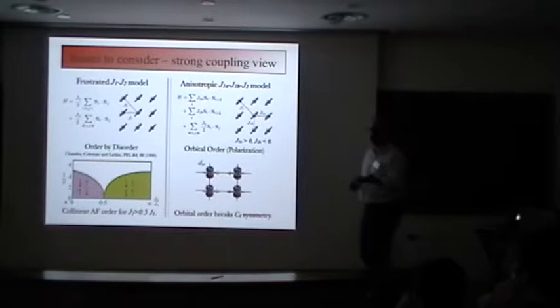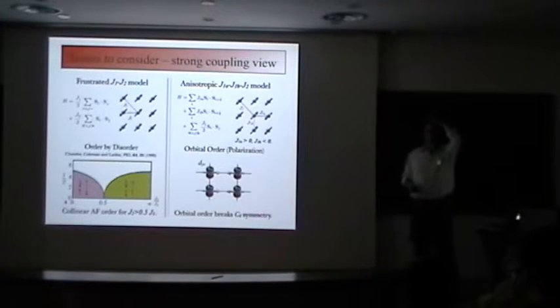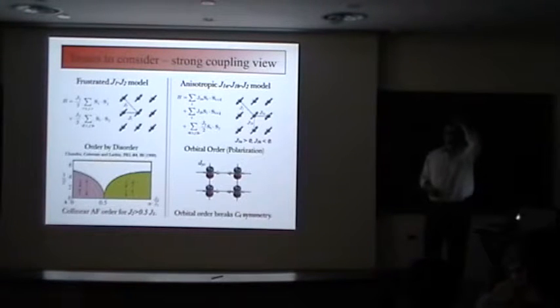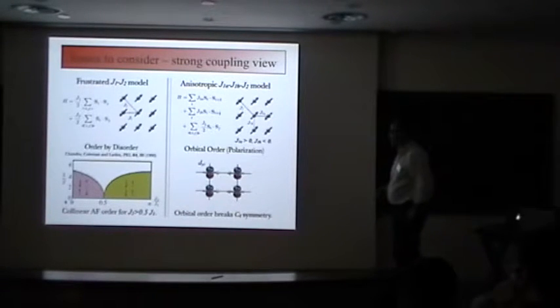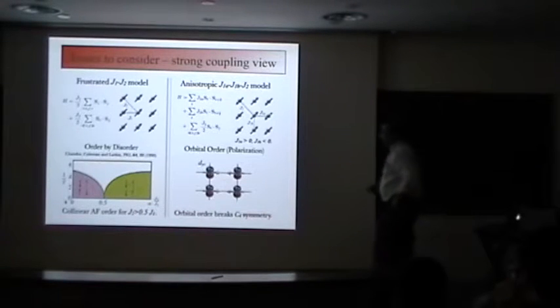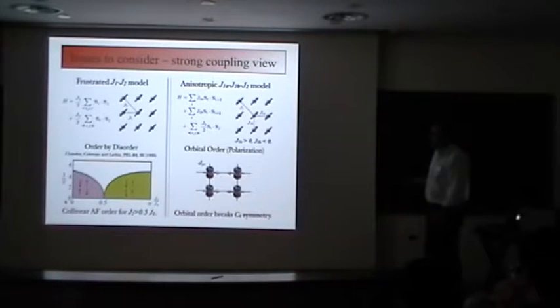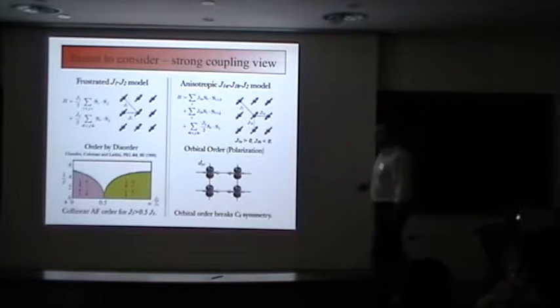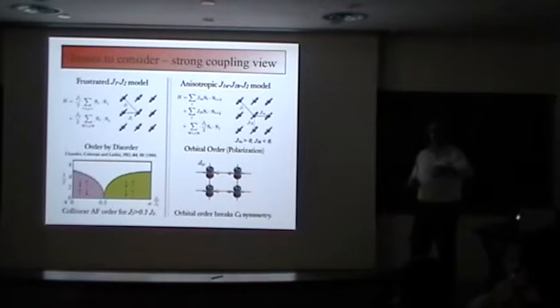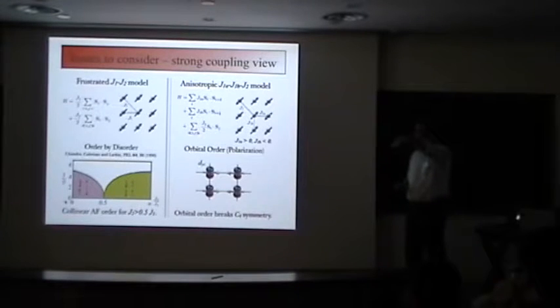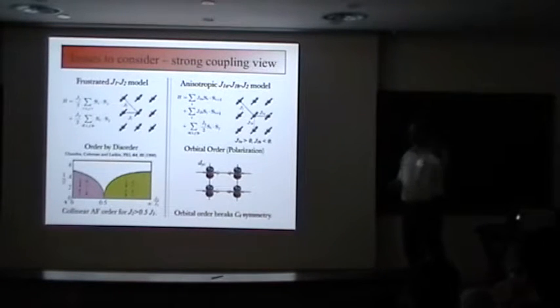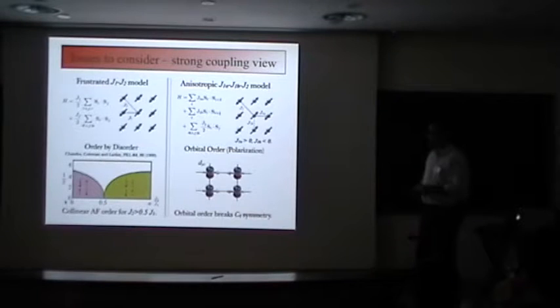The way this could happen is—I was hoping there would have been a discussion about Goodenough-Kanamori rules during the talks, but that hasn't occurred. The way to think about it is if you have orbital ordering where only certain types of orbitals are occupied, then with the same spin you could be blocked from moving to another orbital, or you could promote antiferromagnetic exchange along the other orbital direction. If the orbitals weren't uniformly occupied, it would just be the usual exchange mechanism going from one orbital to the next.